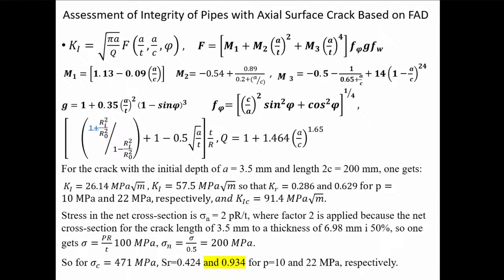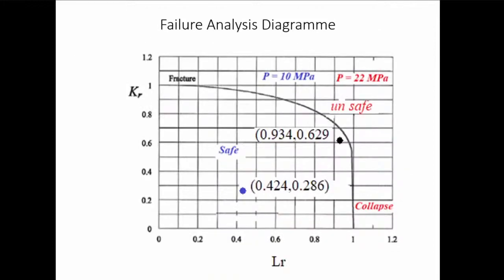here you can see a lot of formulas which are used to evaluate stress intensity factor for axial surface crack. And then we use data obtained here to get the point on failure assessment diagrams. You can see here at the bottom which pressure we have used. One is 10 megapascals, which is operational, and 22 was testing pressure. So for these two pressure values, we get 2 points.